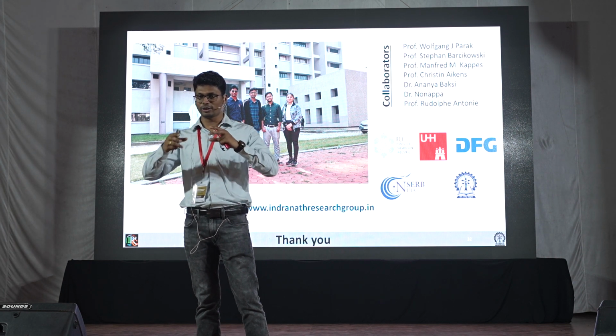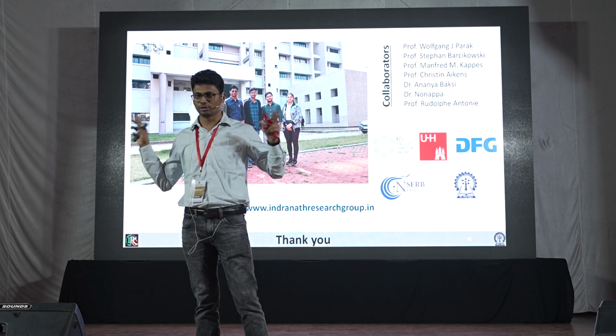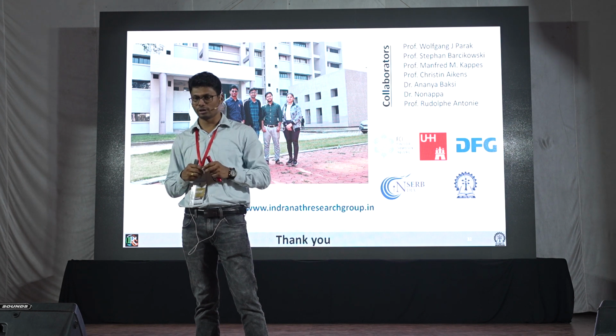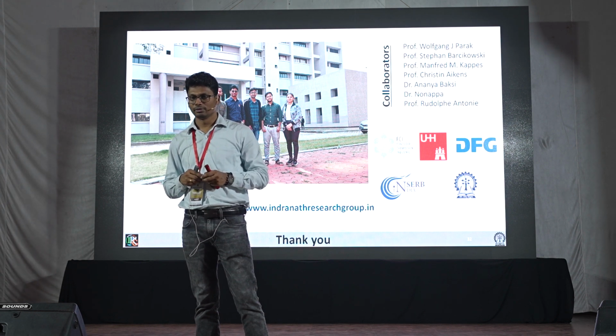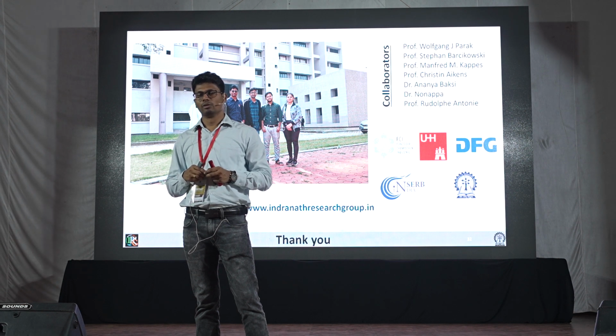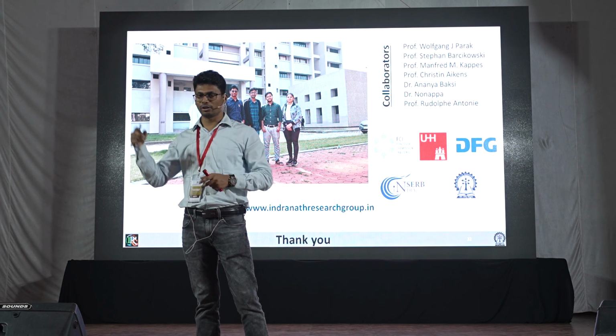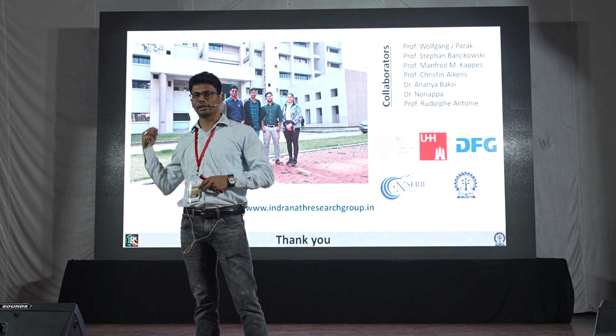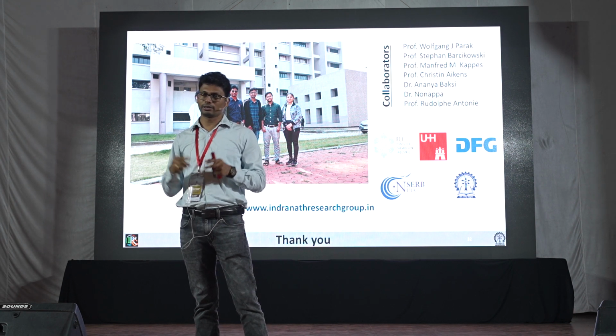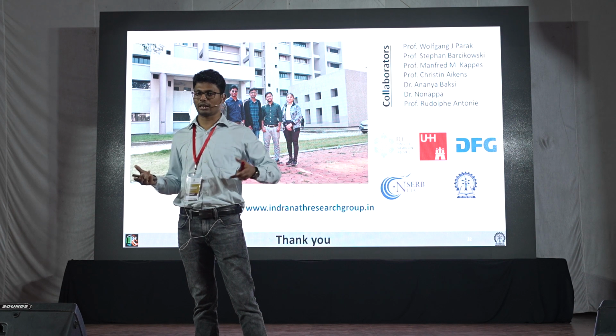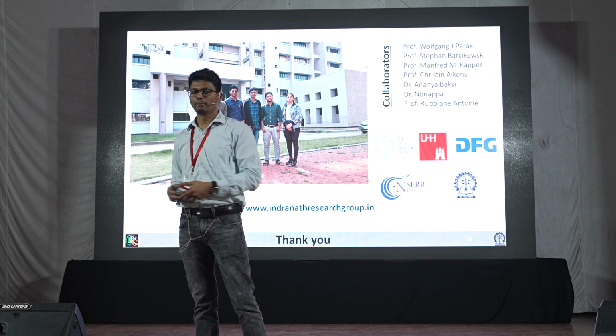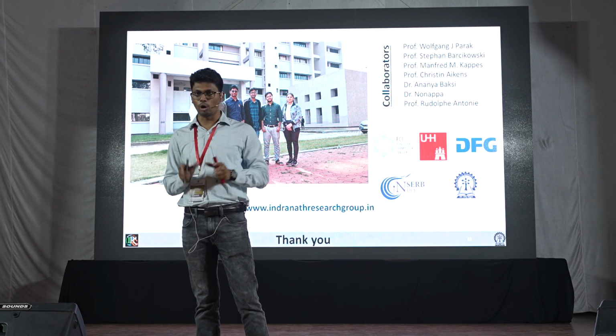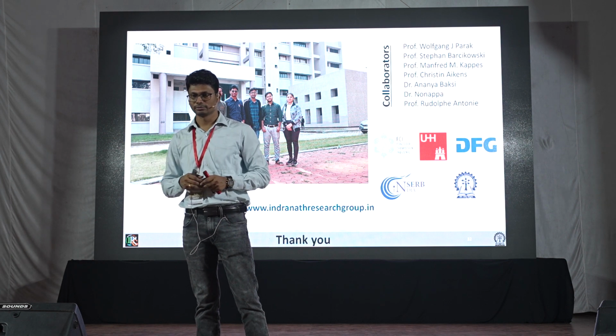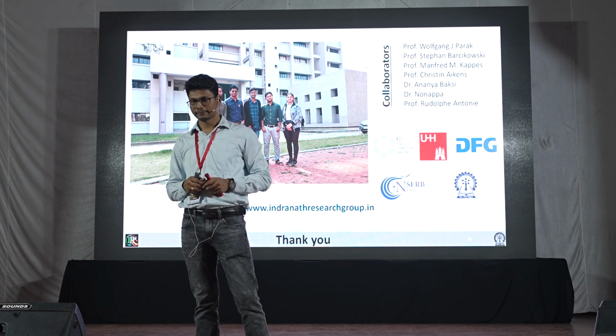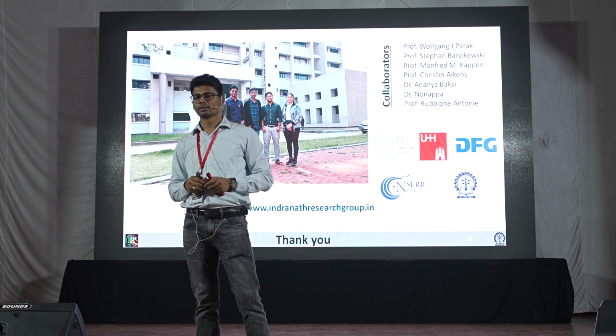That's the dimer I talked about. We saw that in mass spec, yes. Do you have the bond strength, or bond length, something? We did not do any structural characterization of that. We did some experiments and tried to calculate it with a theoretician. But we don't have a crystal structure to know exactly what is happening. From the mass spec data, we thought this could be one of the possibilities. Yes, but generally, carboxylic acid is less likely to be present as a dimer in water compared to an organic solvent, right?